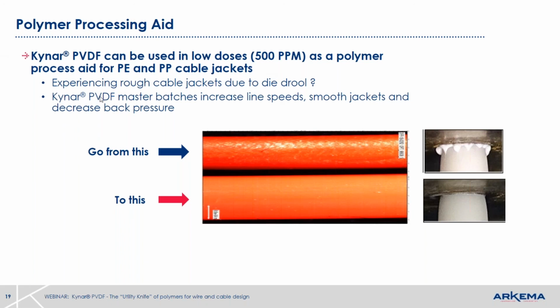batch. So there are master batch makers of PVDF. Just have to tell them what grade of polyethylene or polypropylene you use, and they will match the master batch to that. Again, it's an incredibly small amount of PVDF. It migrates to the outside of the melt stream and allows the polyethylene or polypropylene to slip on through and eliminate the melt fracture and die drool.